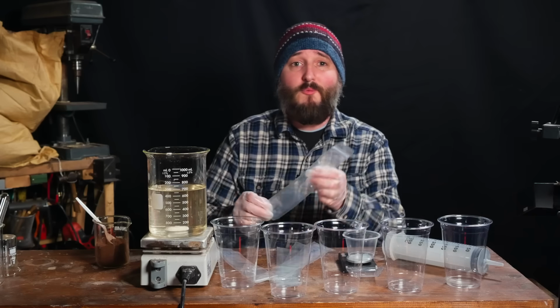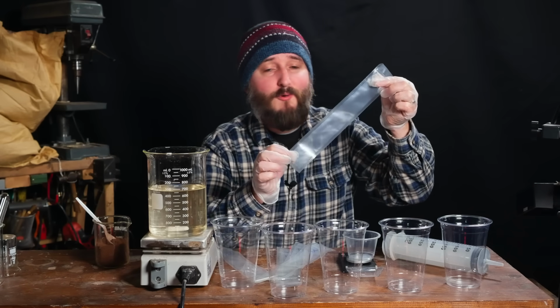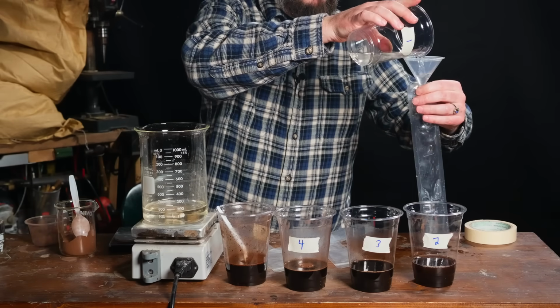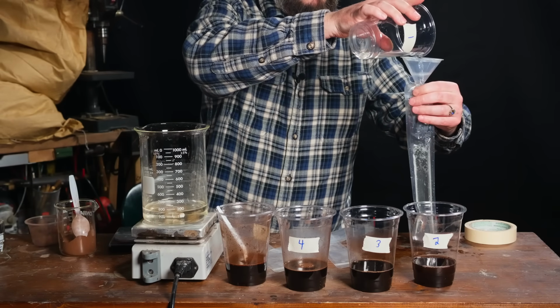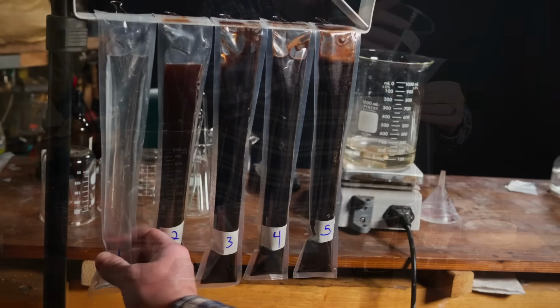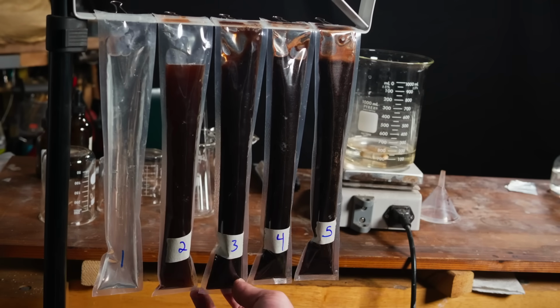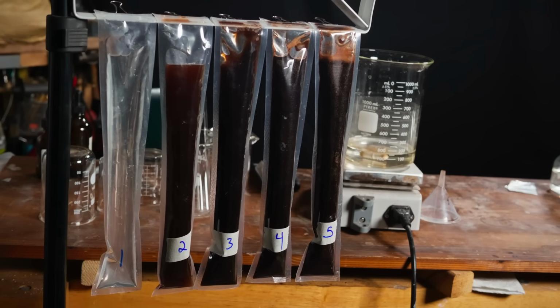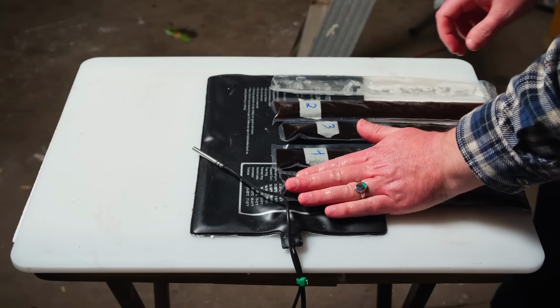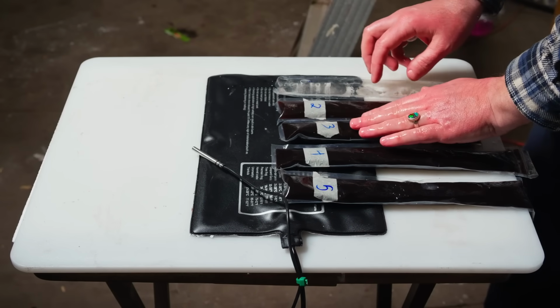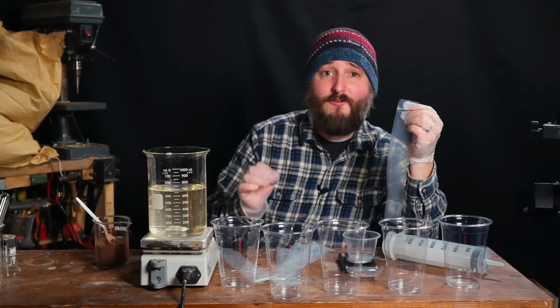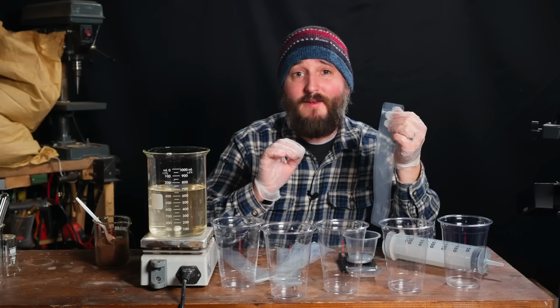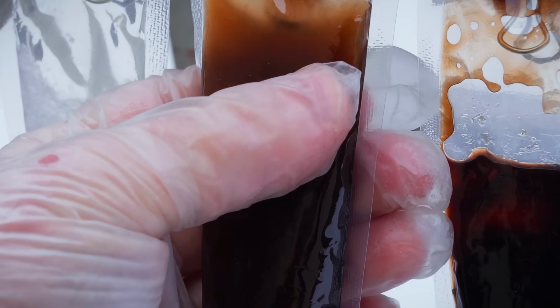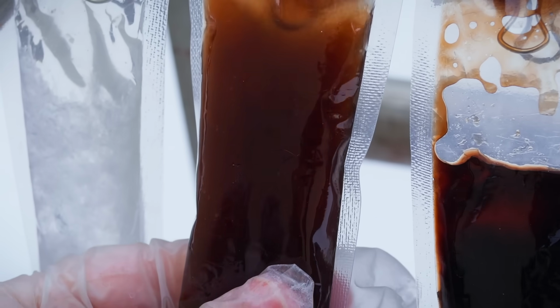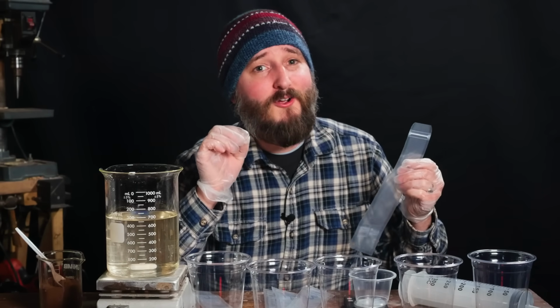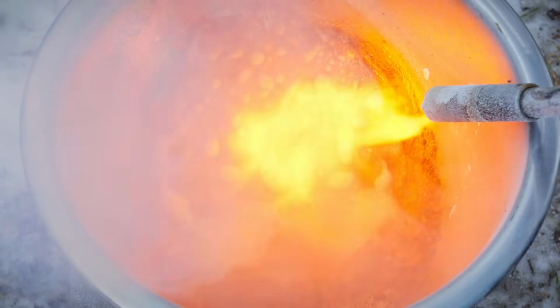The final sample holders will be these plastic tubes, and we'll do several tests with these. First, I'll leave them upright to cool and solidify because that should easily reveal if we have any sedimentation at the bottom or even possible liquid separation effects at the top. Then I'll place the tubes on a reptile heating pad, which I've found is a really good way to stress test a PCM and see if it can resist growing large crystals after repeated cycling. We'll come back and take a look at how these tests turned out at the end of the video, because in the meantime, we have quite a bit more fiery chemistry to explore.